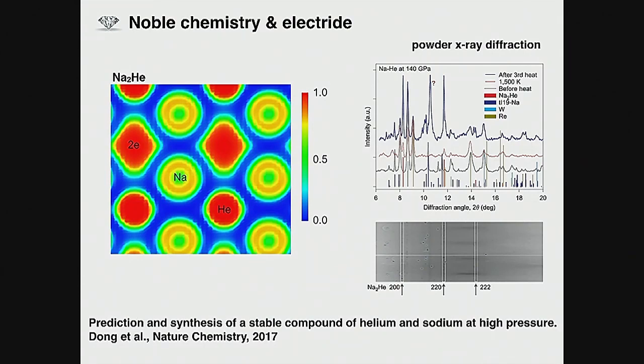So helium is non-reactive, right? Well, this is another active area of research. People have synthesized several compounds of xenon, and also here in this example, of helium as well. Helium in this compound of sodium-2 helium is not just simply trapped in the cavities, which you could think actually happens in high pressure. Sometimes you don't even want it, but hydrogen and helium will penetrate your lattices and become trapped in the interstitial sites. These people, through calculations and then confirmed by X-ray diffraction, show that actually helium is bonded.